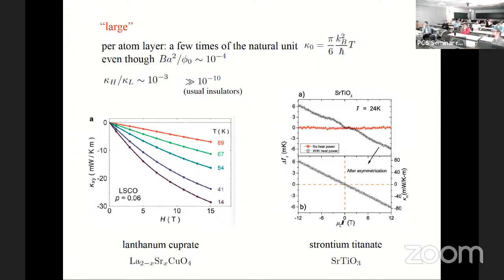So it's large by two standards: large compared to a natural unit, especially when the magnetic field is small, and also large compared to a naive analysis for usual insulators. That is why people in the past didn't think phonons are related to thermal Hall at all, because it's this small. But now we found that it's much larger than the naive expectation for phonon contribution.